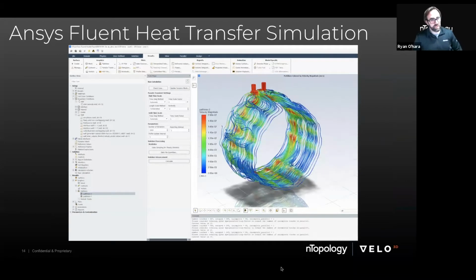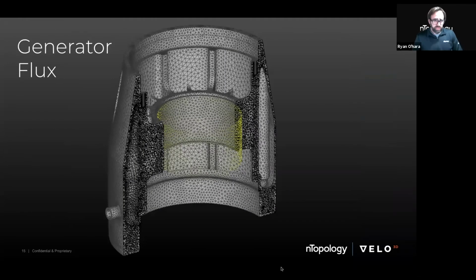And then real simply, we took the internal geometry, and this is the ANSYS Fluent heat transfer simulation that we did. We're able to calculate this heat transfer at the walls, and I was able to apply that as a boundary condition in our software. And just real simple, in this scenario, we took the part that has been shelled, we generate an FEA mesh inside of nTop platform,